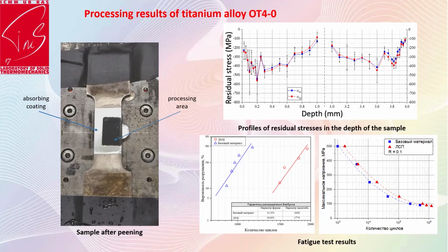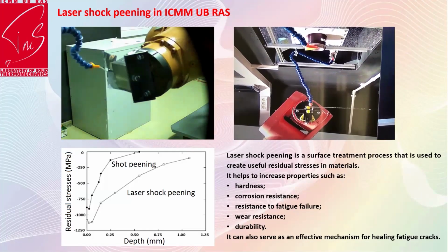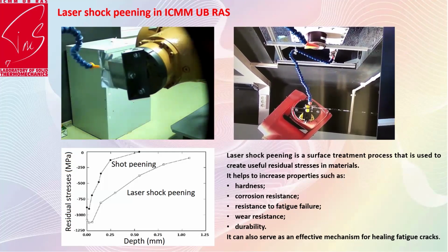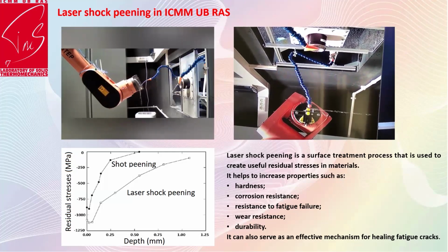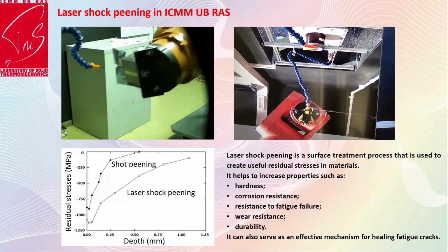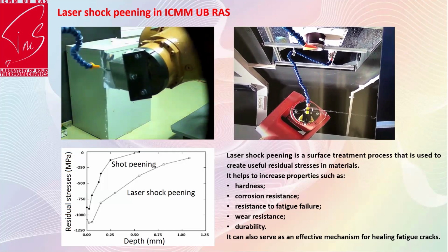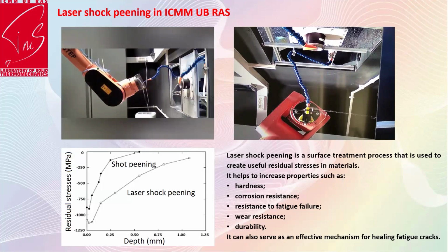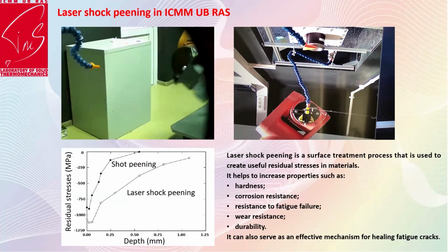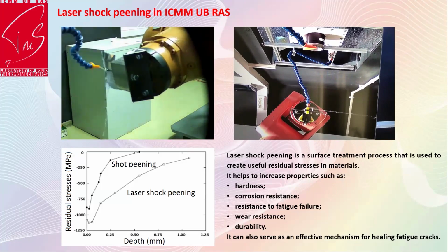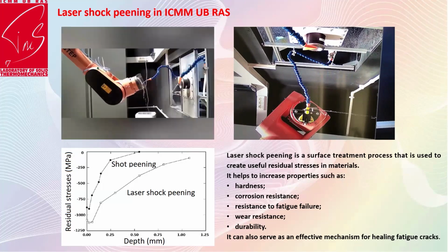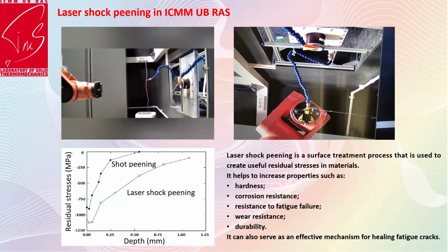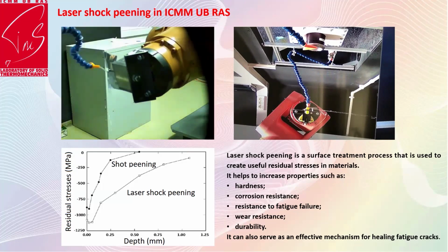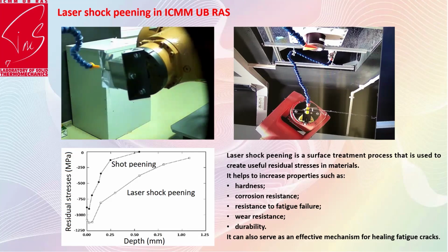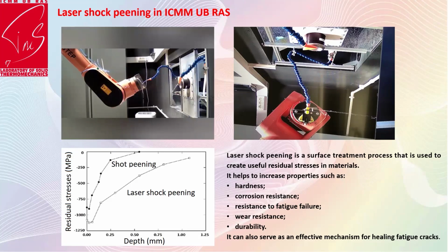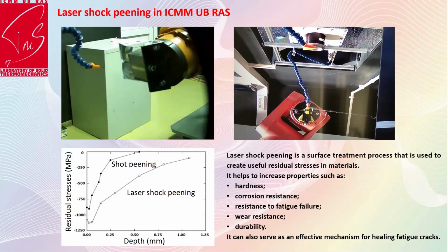And we decided to start this work in Russia. Now we have an experimental setup. We can treat practically any shape of samples, any materials. The power density in this setup is bigger than the setup in the United States. And if you read about this technique, it's really a magic wand. You can increase hardness, corrosion resistance, fatigue life, wear resistance, durability. You can heal a fatigue crack. You can do all what you want. It's absolutely fantastic, but it's too good to be true, of course.